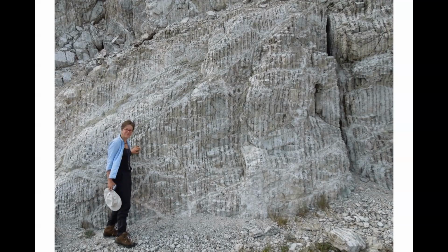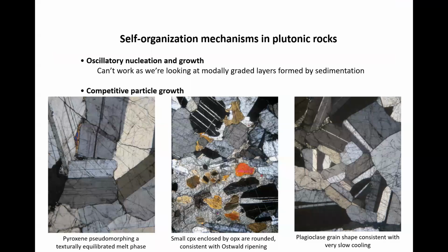And the idea is that the competitive particle growth was triggered, A, because the Stillwater cooled fantastically slowly, and B, you could have a reduction of grain size due to infiltration of metasomatic fluids, which triggered some sort of partial melting and a melt back and a grain size reduction. So Alan's done some very nice numerical modeling of this and can generate these doublets by competitive particle growth. So I looked at the microstructures in here and they totally fit with this model.